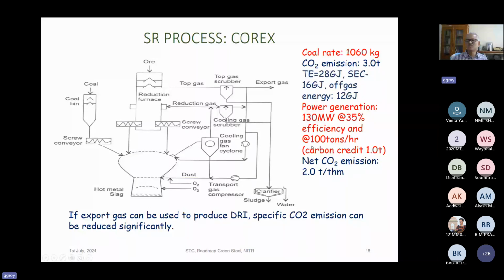hour, then the carbon credit from the power generation can be 1 ton of CO2 per ton of crude steel. That is basically from calculation, you can simply calculate, and then the net emission becomes 2 ton per ton of hot metal. And if the export gas can be used for the DRI production, then the specific CO2 emission can be reduced more than that.